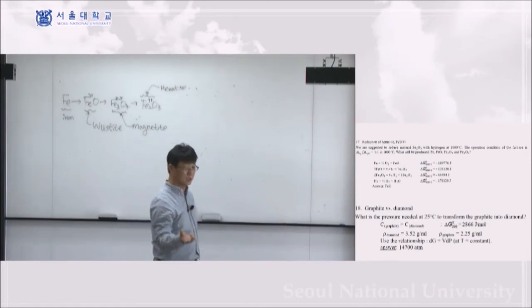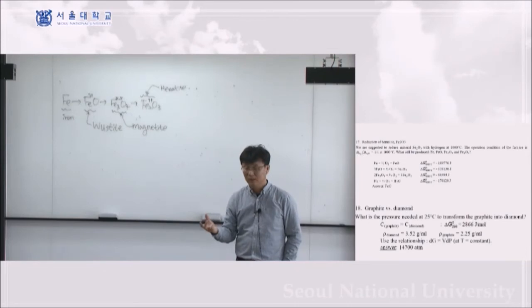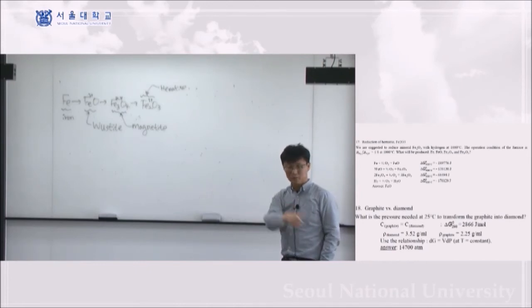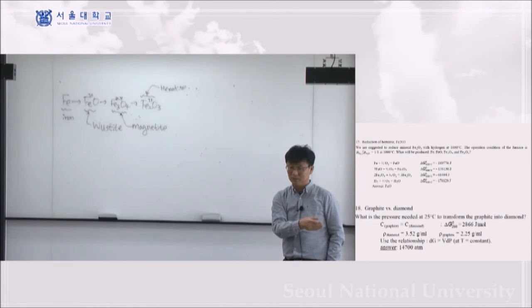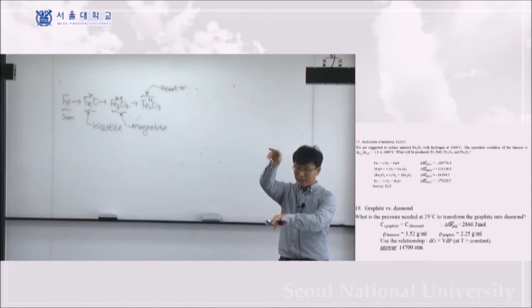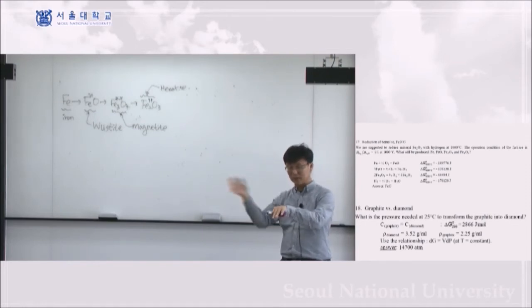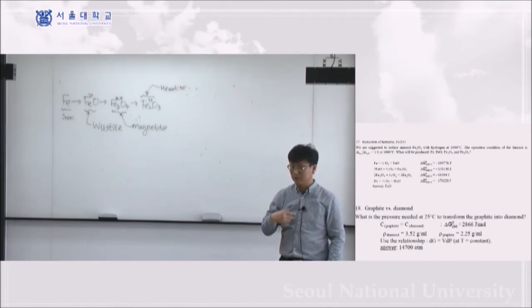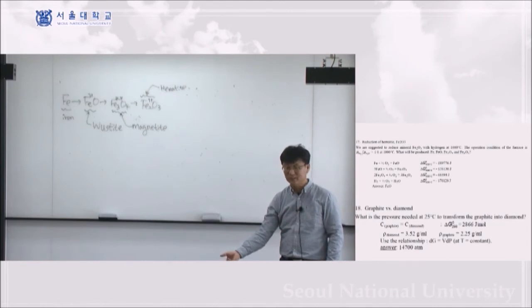Okay? So you have nickel and nickel oxide. Well, you have nickel, and then I have this partial pressure of oxygen condition, CO/CO2. Is this nickel going to become nickel oxide or stay nickel metal? So I have gas and then metal. Under the gas condition, there will be a certain partial pressure of oxygen, and that makes a chemical reaction with the metal. Is that going to be a forward reaction or a backward reaction? I'm not asking you what the final state is. I'm asking you whether this reaction goes forward or backward.